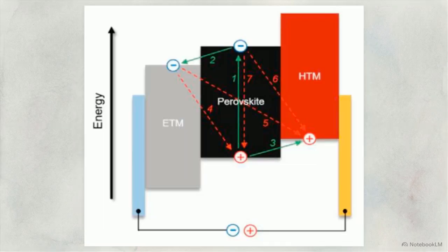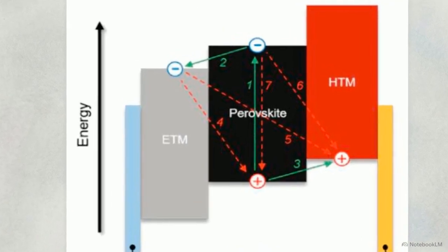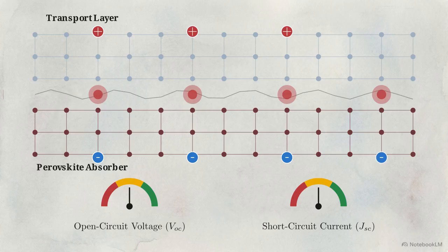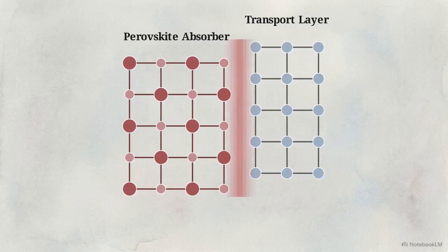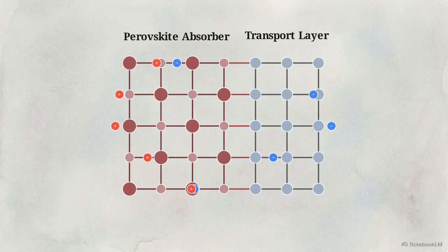In this energy diagram, the central perovskite absorber relies on strict alignment with the transport layers. Light splits charge carriers down the cascade, generating voltage. But misaligned boundaries create interfacial traps where electrons and holes recombine, destroying the cell's efficiency. Minimizing these exact recombination pathways is the primary method for maximizing both the open circuit voltage and the short circuit current of the device. Efficiency depends on the integrity of this energy cascade, a chemical sequence where the quality of the boundary dictates the performance of the whole.